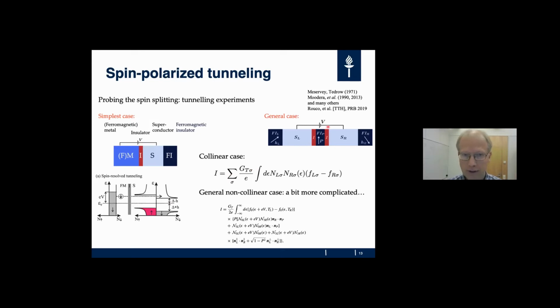We recently studied sort of the most general case here, where you have two spin-split superconductors coupled via a spin-polarized interface. In principle, the magnetizations in these three cases can be non-collinear, and you can study what happens to the tunneling characteristics. Then the tunneling formula becomes a bit longer.